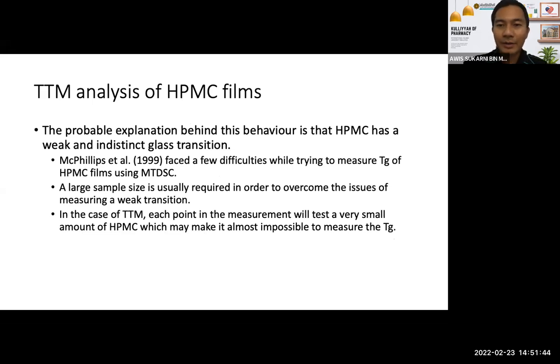So the probable explanation behind this behavior is that HPMC has a very indistinct, very small glass transition. Even when you run it using the DSC, sometimes it's quite hard to find the transition temperature of the HPMC. This has been reported by McPhillips. They found, when they ran the HPMC using the MTDSC, and so he concluded that we need to use a large sample size in order to measure the transition temperature of the HPMC. In the case of the TTM, we are looking at a very small amount of the HPMC because it's just at the tip of the probe, which is less than 30 nanometers in size. So it makes it almost impossible for the TTM to measure the glass transition temperature of the HPMC.